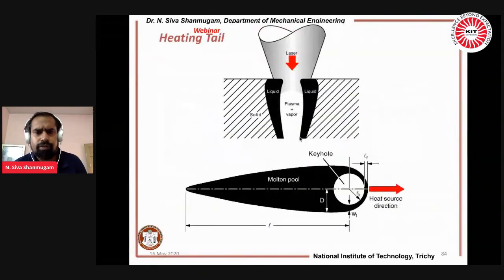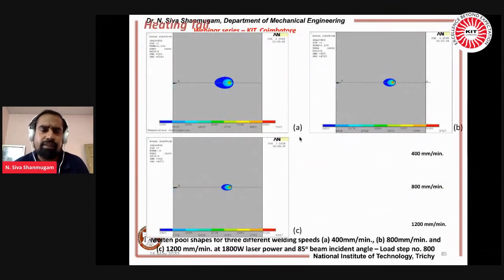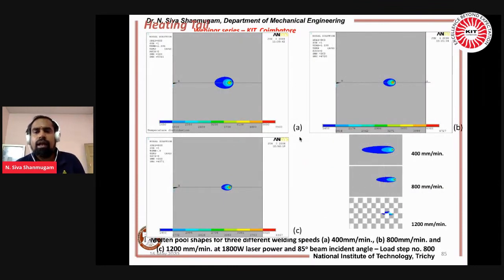So I think this is a quick brush up. This is the thing we have discussed, so much about the preheating zone and the post-heating zone. See, with a very low welding speed, 400 mm per minute is very slow compared with 1200 mm per minute, you have a very big heating tail. So the preheating zone is very minimal, and you have a very big heating tail.